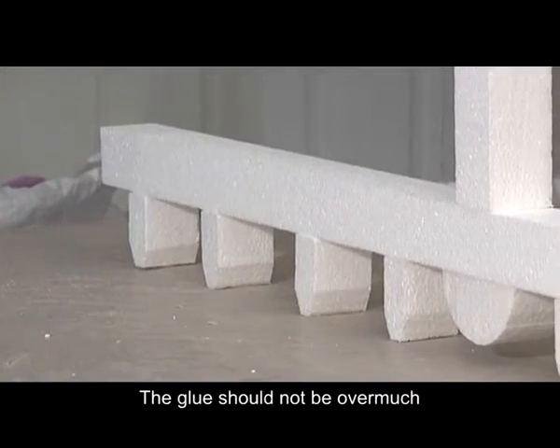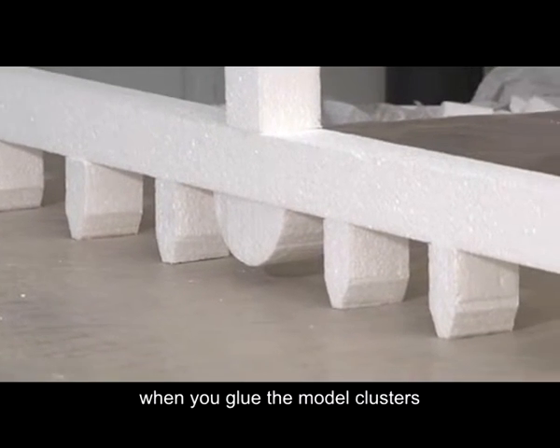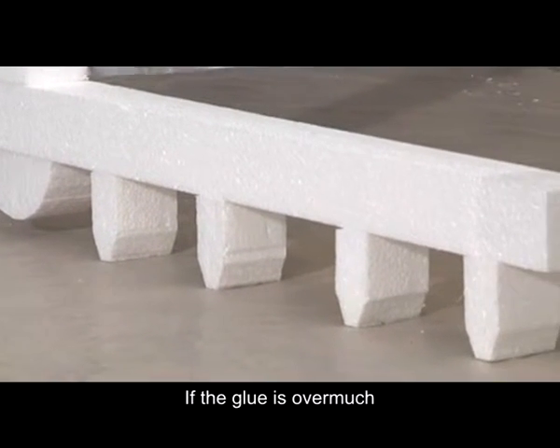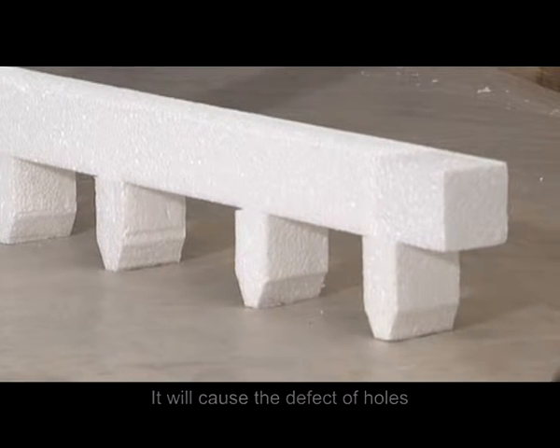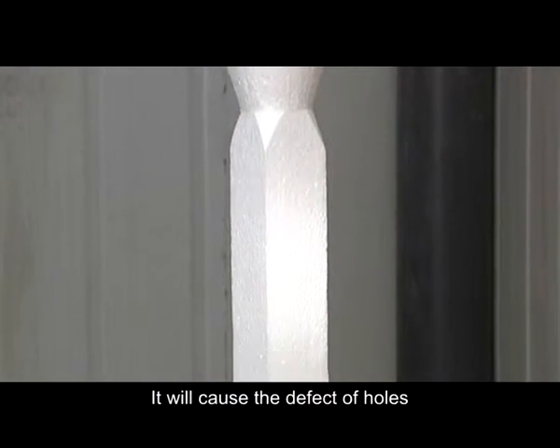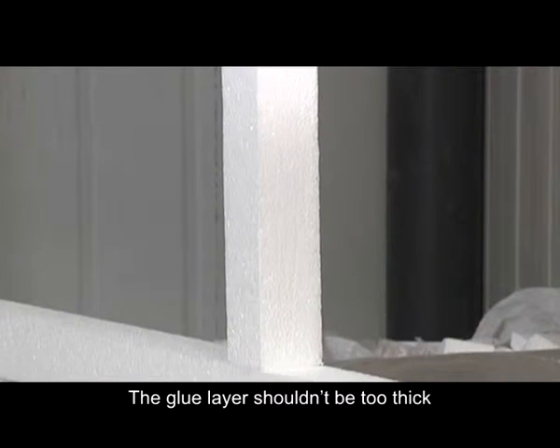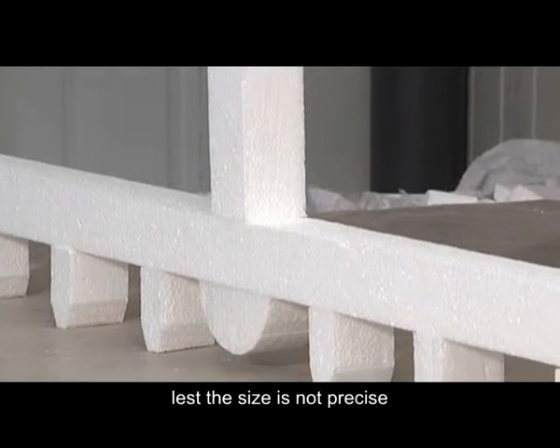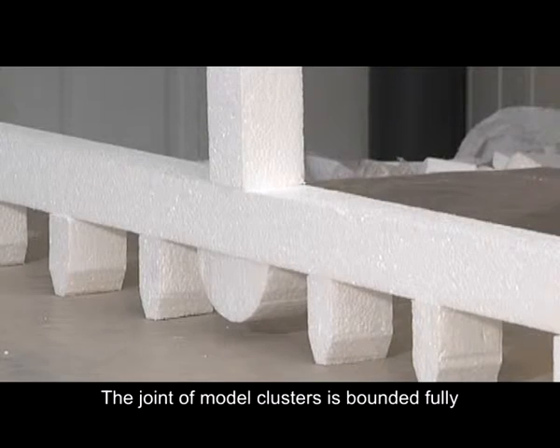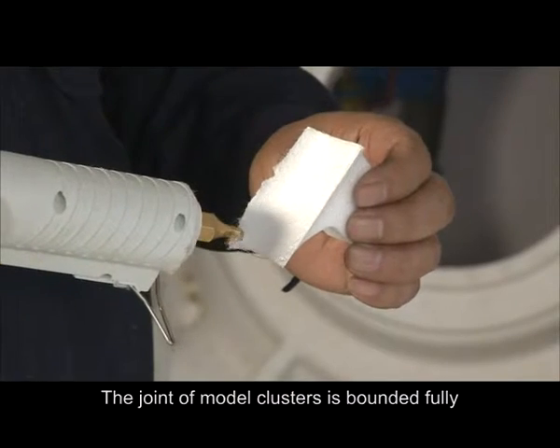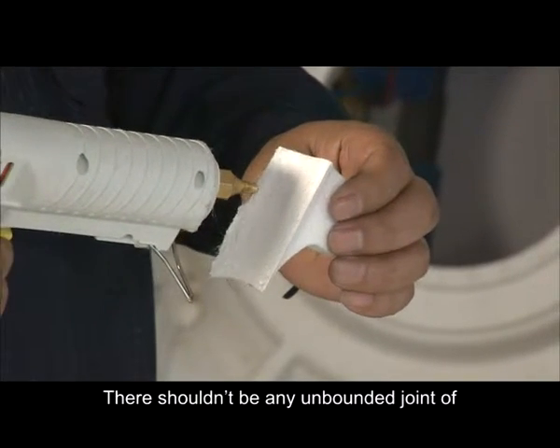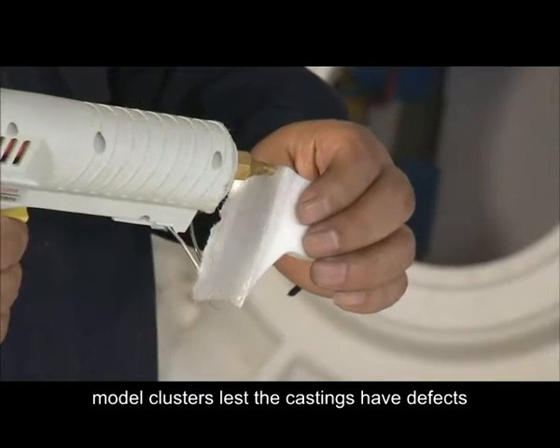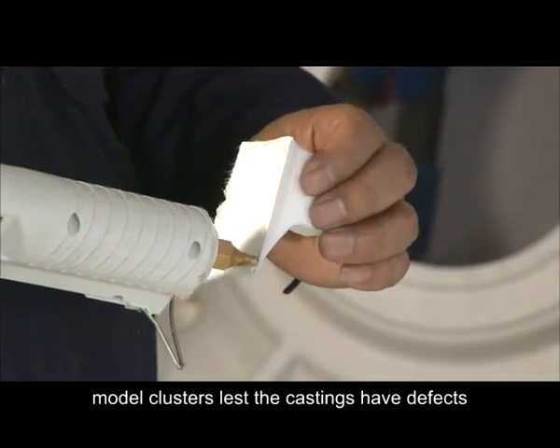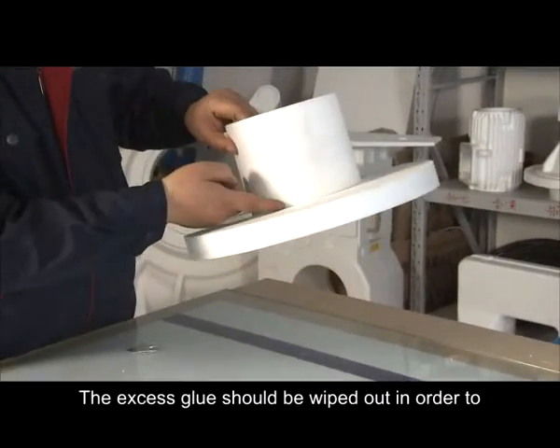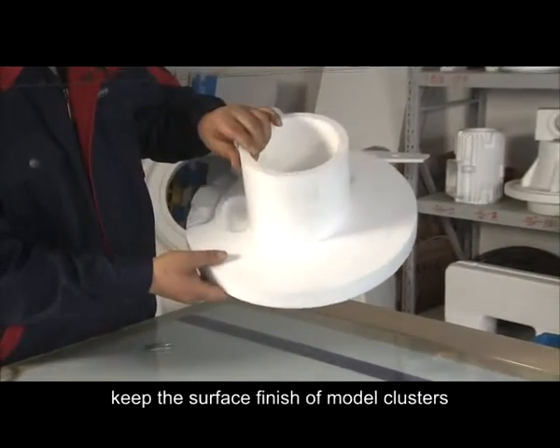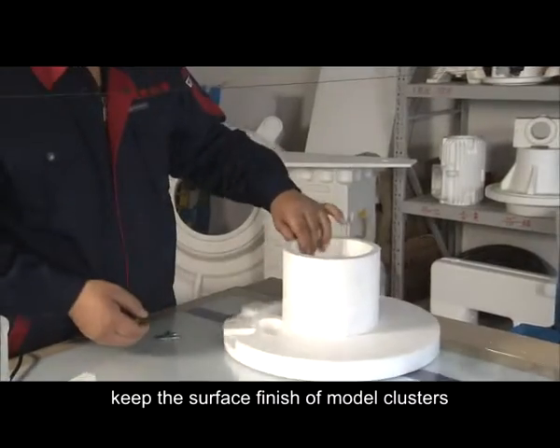The glue should not be overmuch when you glue the model clusters. If the glue is overmuch, more gas will be produced, which will cause the defect of holes. The glue layer shouldn't be too thick, lest the size is not precise. The joints of model clusters should be bonded fully. There shouldn't be any unbonded joint, lest the castings have defects. The excess glue should be wiped off in order to keep the surface finish of the model clusters.